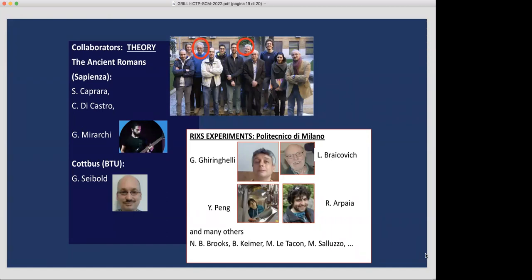This came up, interestingly enough, in the context of a cerium system, cerium rhodium germanium, which is a ferromagnetic strange metal. And one of the questions was whether the log T was coming from ferromagnetic fluctuations or was non-Fermi liquid behavior. And the prefactor was much too big to explain it in terms of a coupling to spin fluctuations around the Fermi surface. It looks more local in character. So the prefactor is a very important signature of the possible origin of the log T behavior, I think, anyway. Yeah. Cheers. Nice talk. Thank you.